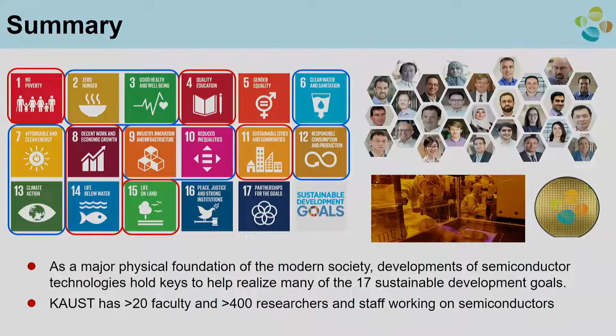From Kang: I have a basic question. Why do wide bandgap semiconductor devices generate less heat than narrow bandgap semiconductors? Yeah, right. I showed a figure earlier. Basically, it is resistance compared to voltage. For a wide bandgap semiconductor such as gallium nitride, if you compare that with silicon, at a certain voltage, such as 1,000 volts, its resistance is about 3 orders of magnitude lower compared to silicon. We know that the amount of heat you generate when the current runs through is proportional to the resistance. Because you have 3 orders of magnitude lower resistance, gallium nitride and other wide bandgap semiconductors will generate less heat compared to silicon.